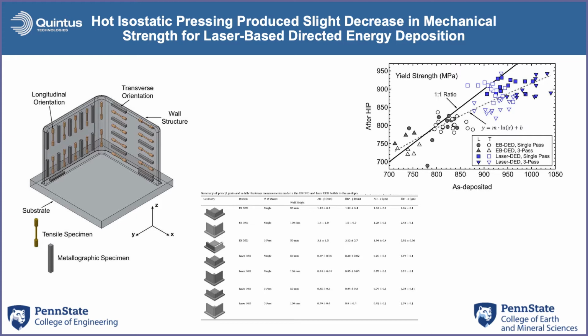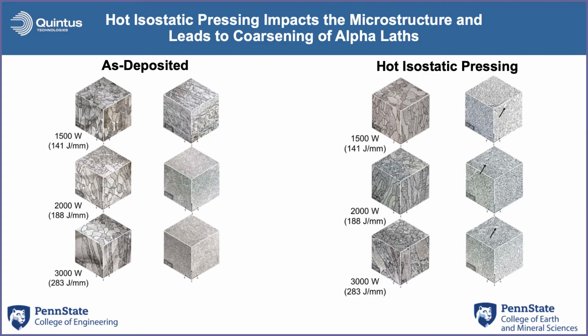And being able to hot isostatically press those and to really see the importance of hot isostatic pressing in reducing uncertainty in mechanical properties. Whereas when we look at as deposited or as built properties in Ti 6-4, they are spread out all over the place. There are huge variations in the properties. And when you hot isostatically press them, those variations tend to get a lot narrower. And it's much more of an attractive range of properties for designers than what the current as deposited materials are.